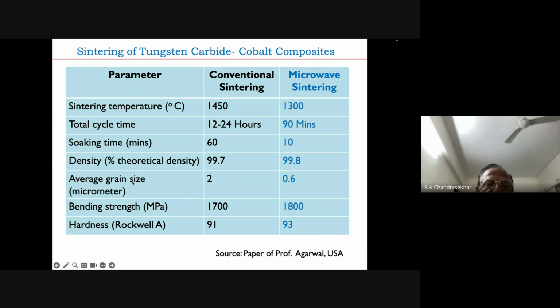Average grain size has reduced from 2 to 0.6 - a tremendous advantage, because as you reduce the grain size, the mechanical strength properties, the hardness and other things improve dramatically. The bending strength has improved and the hardness also has improved. This is the power of microwave sintering.